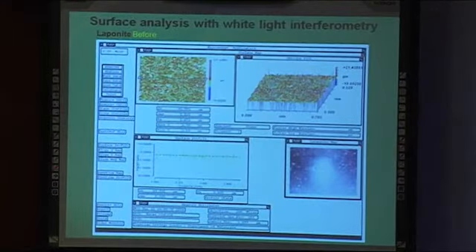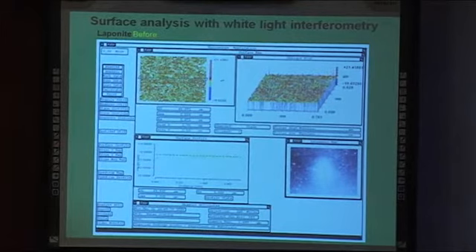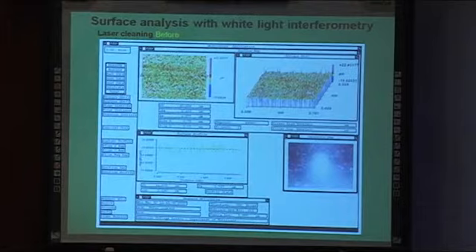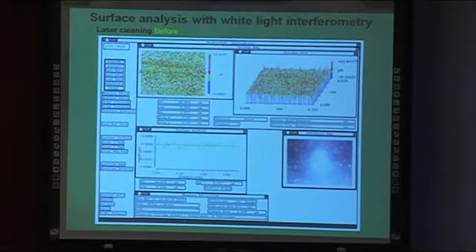The next 4 slides will show the results of analysis of plaster controls before and after surface analysis with white light interferometry. The examples I have chosen to represent here are the 2 methods which most and least altered the surface roughness. This slide shows the results before cleaning with 3% Laponite and 3% fumed silica applied over wet alkaline tissue and lifted off. This is after the cleaning, showing the difference in surface roughness. The next 2 slides show the insignificant difference of 0.438 microns before and after laser cleaning.